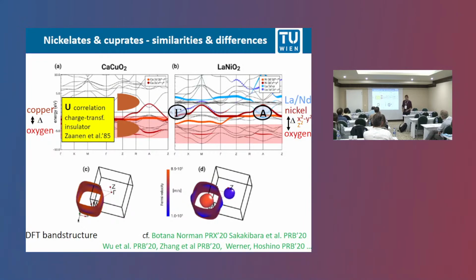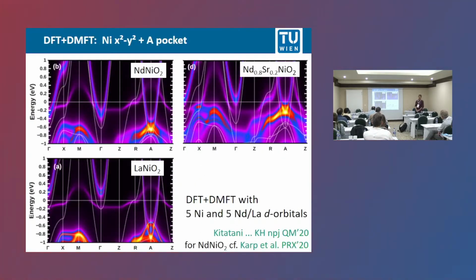Again, this was just a DFT picture, and now we have to think what correlations do, as for the cuprates, where you get a charge transfer insulator. And to this end, we have done DFT plus DMFT calculations based on all nickel and all neodymium 3d and 5d orbitals. And if you can see it from the back here, what you see is first of all a strong quasi-particle renormalization. So that white line here is the DFT band structure, and you get a renormalization by about a factor of 5. You also get some finite lifetimes, therefore you have these broadened energy levels.